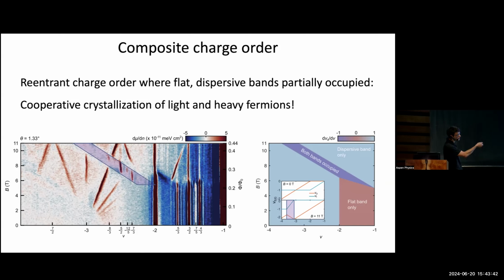So if you just go from 11 Tesla and add the number of holes to your system, you start off occupying dispersive bands, dispersive bands, dispersive bands until you hit this spot right here and you start filling states in this purple region. And actually you start to empty holes in the dispersive band and start to fill them in the flat band. And so you change this occupancy, and actually within this purple window, you have partial occupancy of both flat and dispersive bands.